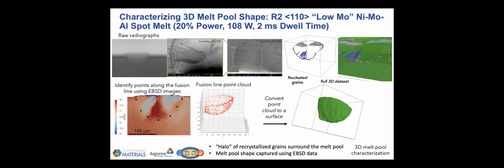If we had columnar to equiaxed transition, we would expect to see subgrains penetrating down more into the melt pool, right? And so that was a flag to us that in this particular case, we don't necessarily have the columnar to equiaxed transition. And we have to be really careful about that in the different melt pools that we're analyzing. In other melt pools, we actually don't see this sort of recrystallization that we see in this one particular example. But again, we want to be very thoughtful about when we have CET or not, and we really need to look at the microstructures in more detail to confirm that kind of a finding.